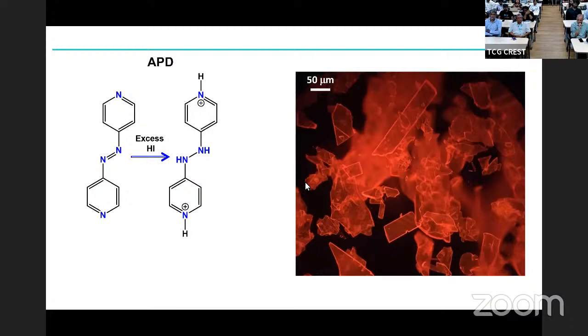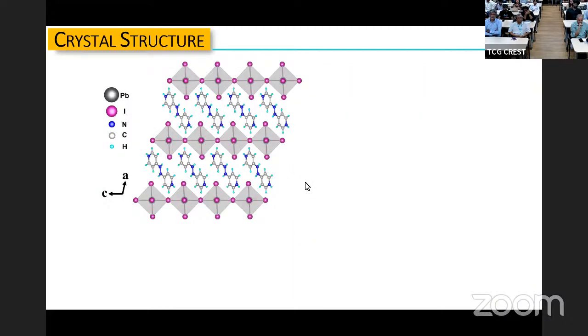This is called APD, azopyridine, essentially. And this is a crystal structure. So you basically get these inorganic layers separated by these organic layers. I'll not belabor the point that there's a structural peculiarity of this. It's a two-headed molecule that you have taken, and yet this layer is staggered with respect to that one, which I say is normally realized only with a one-headed organic molecule. But I'll not go there.